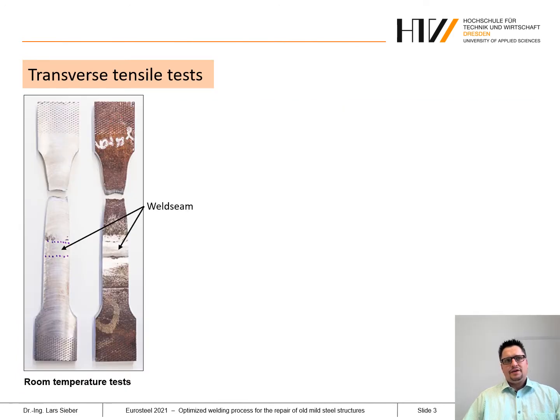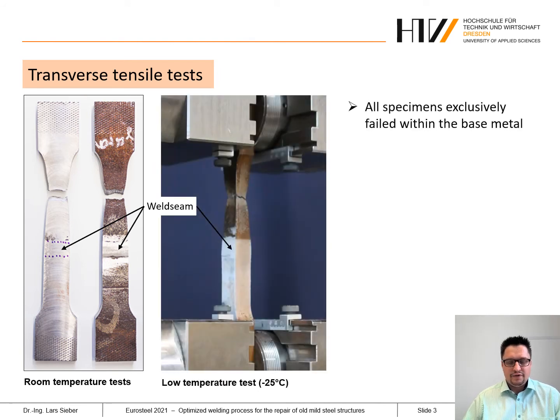As explained in Copenhagen, all the transverse tensile specimens of all welding samples exclusively failed within the base material. You can see here the weld, and here the specimen failed. This fracture behavior also occurred in all further experiments over the 3 years, including the tensile tests at lower temperatures, which you see here at minus 25 degrees Celsius. This means that the strength and also the ductility in the heat affected zone as well as in the weld itself must be higher than in the base material.